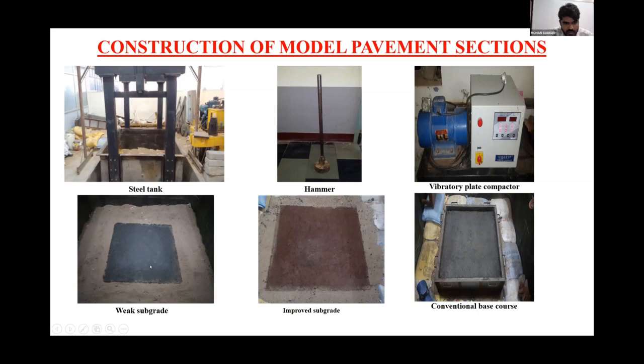In the bottom row, we have the first image, which is of construction of weak subgrade, which is of 300 mm. And on either side, we have laid sand, which is compacted to a relative density of 80% to simulate the shoulder. And we have a 100 mm thick improved subgrade compacted over the weak subgrade. And over that, in case of the unreinforced section, we have laid the base course directly.